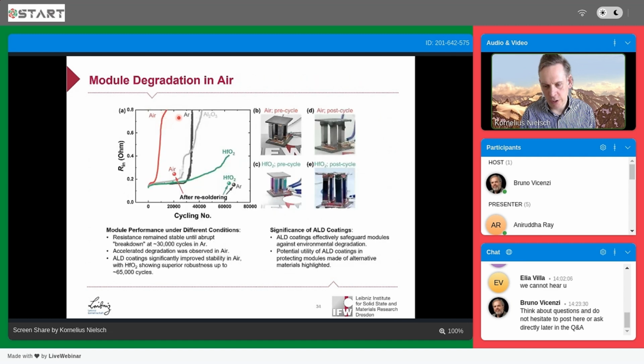For the next test, we directly applied atomic layer deposition, which has a very nice feature: that we can coat any kind of three-dimensional structure. So we take these fully assembled modules and put them in an atomic layer deposition reactor. You can also easily upscale this process, coating, for example, several tens of modules within one run. And we used two different material systems to test the stability of our modules.